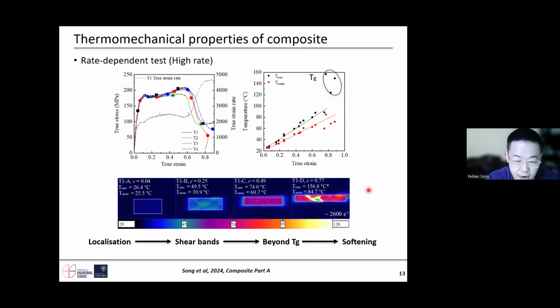After testing, I collected the test sample. We cannot see very evident crack or failure. So I took the sample to ESRF to do the measurement. Through that measurement, we didn't see any failure or debonding during the in situ X-ray measurement.